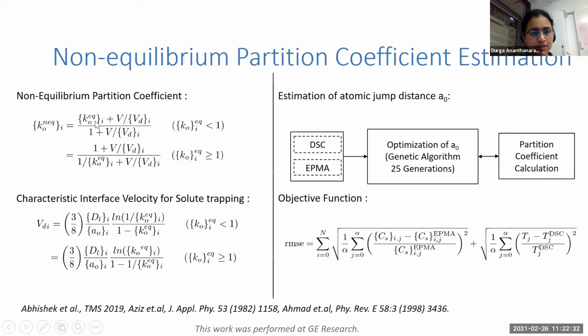So as I said, it's related to the equilibrium velocity and the diffuse interface velocity. And this diffuse interface velocity itself is related to the diffusion coefficient and also this A0, which is called the atomic jump distance, which is related to the interface thickness. So this is something that we cannot easily estimate experimentally, and therefore it can be treated as a parameter in our models, and we can try to estimate it if we have good data. So that's what we did.